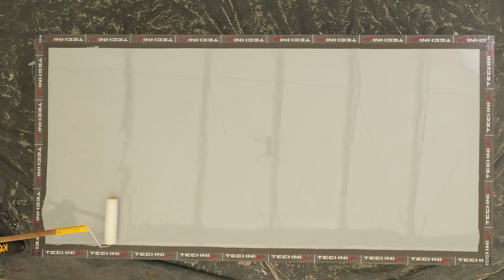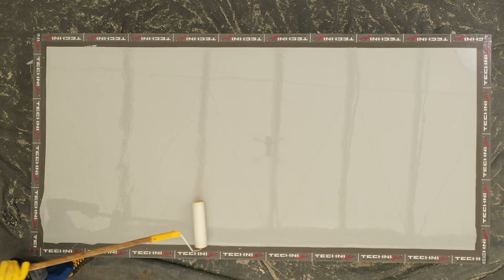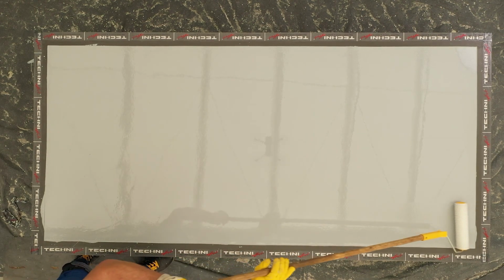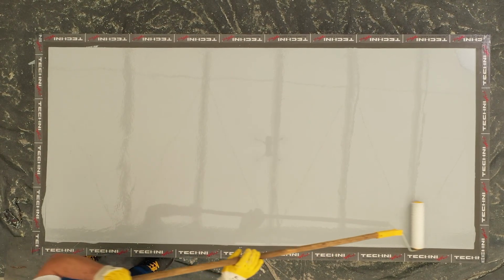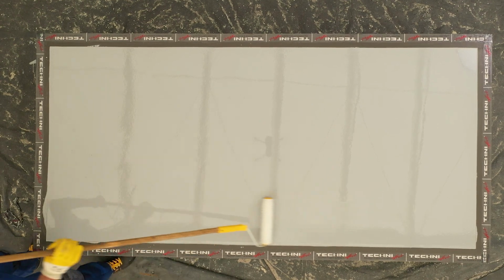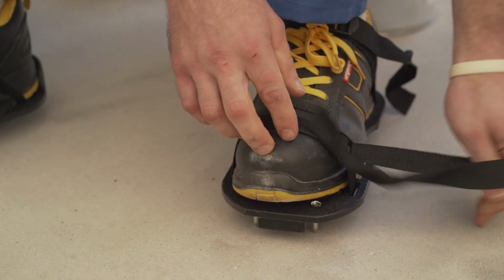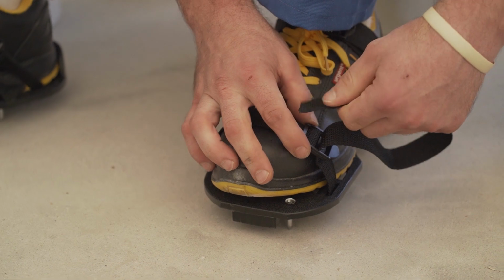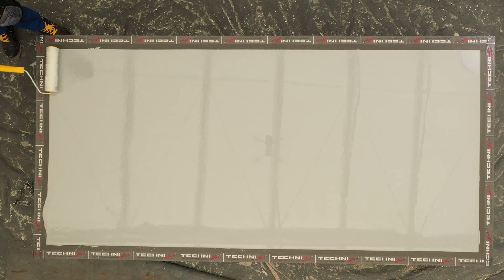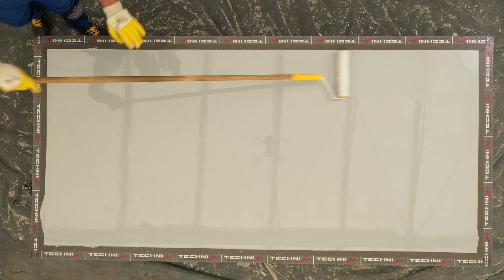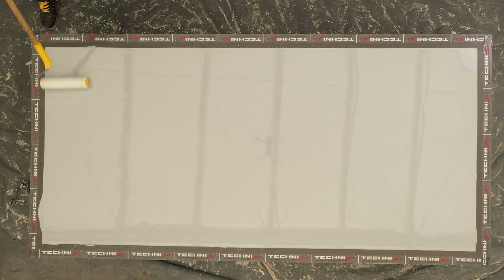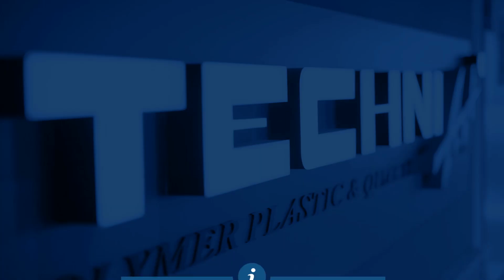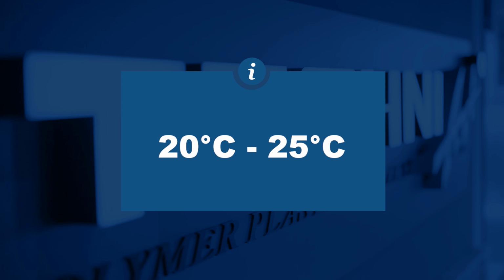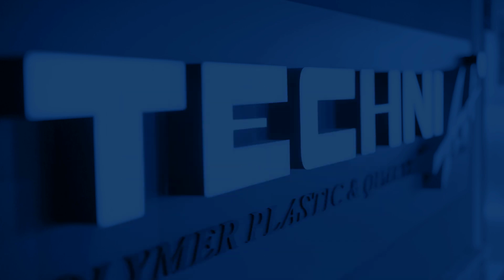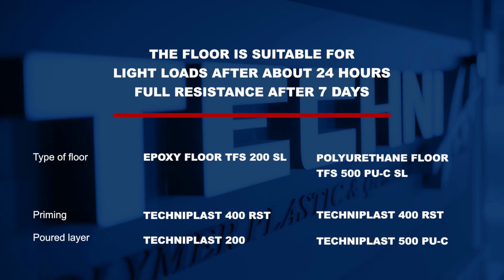After the material is evenly distributed over the entire planned surface, you should immediately start venting the floor with a spiked roller. You should remember to use spiked shoes, as you will need to walk on the freshly applied resin. The floor should be carefully rolled, using the cross method, until a uniform surface is obtained. Provided that it is cured at a temperature between 20 and 25 degrees Celsius, the floor is suitable for light loads after about 24 hours and obtains full resistance after 7 days.